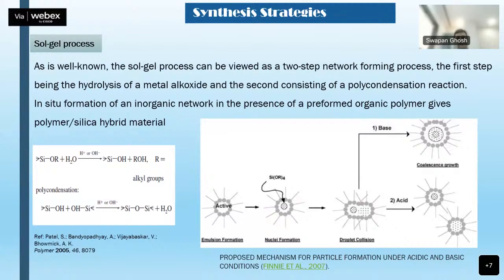So you can have the active, stabilize it in an emulsion, and then a silicon precursor will be added to it. And finally, when stirring is given, a lot of particles will come close together, they will hit each other, and they will have some sort of collision. From that collision, we have two ways to work: one is adding a base, another is adding an acid. In both cases, we have different morphology, but the active ingredients, whatever we are talking about, will be coated by the silicon precursor, that is, the silicon oxide particle. And here also you can form different types of morphology.